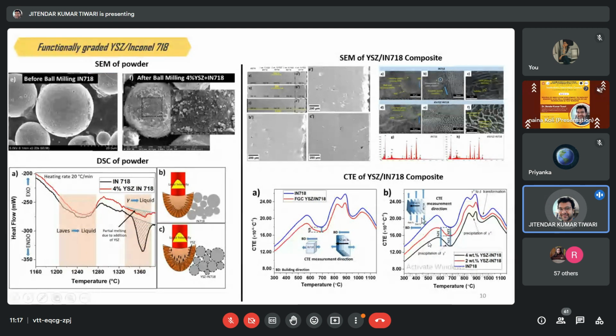But when we are observing, sorry, here we are observing it along the composition gradation, and here we are evaluating it perpendicular to the composition gradation. So here the variation is much higher, because here the equivalent composition of yttria stabilized zirconia comes into the picture. But here, if you see, the individual composition of yttria stabilized zirconia is playing a very important role, and you might observe some fluctuation in this curve.